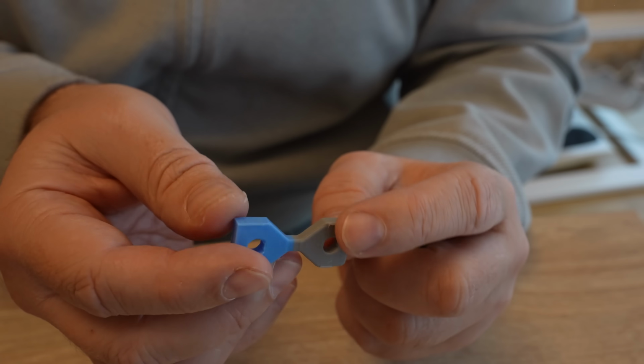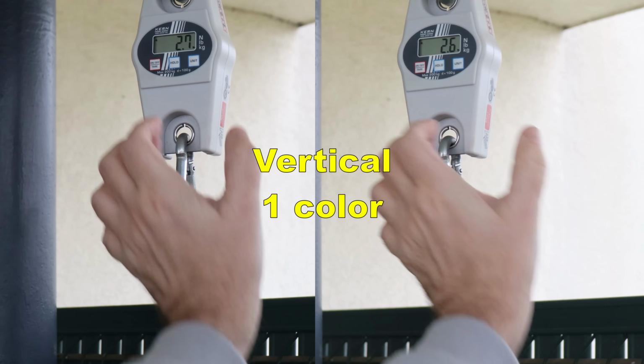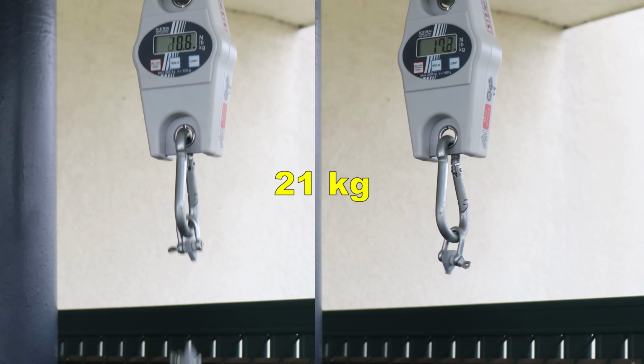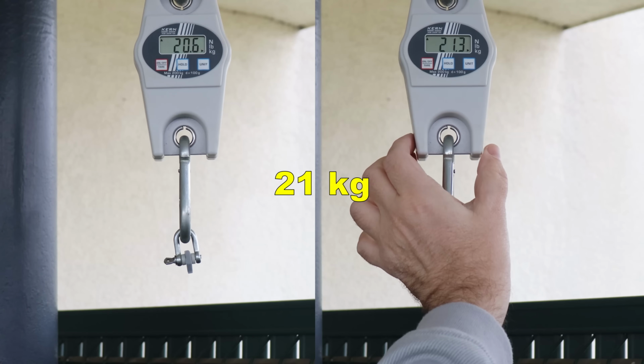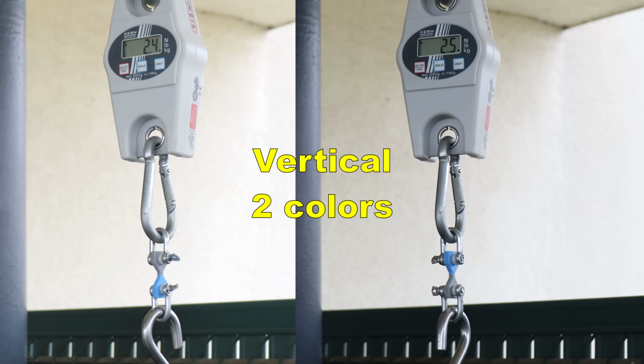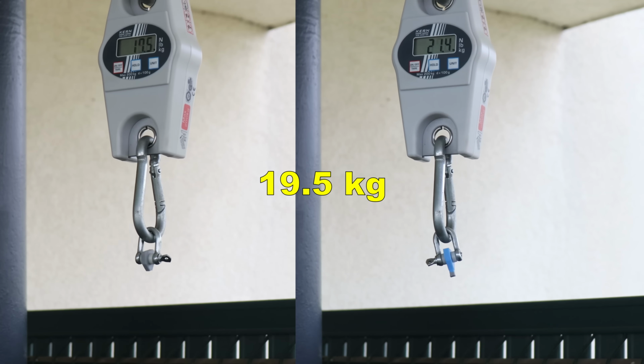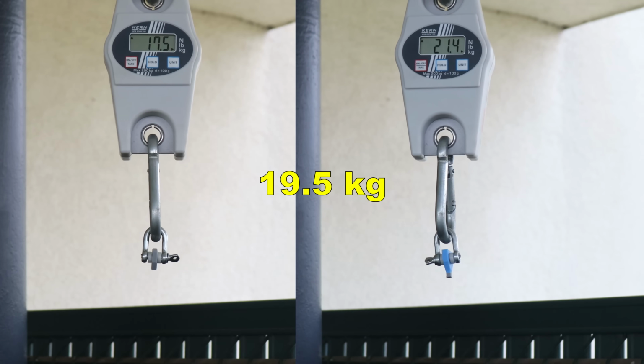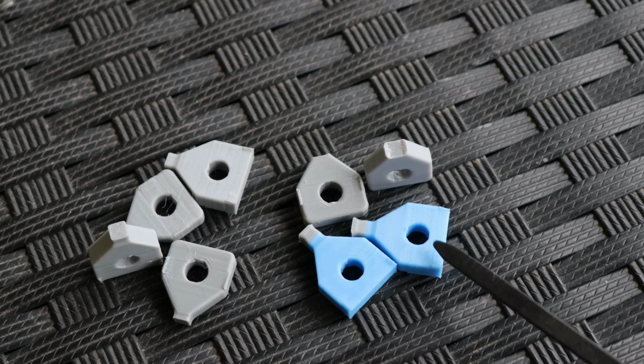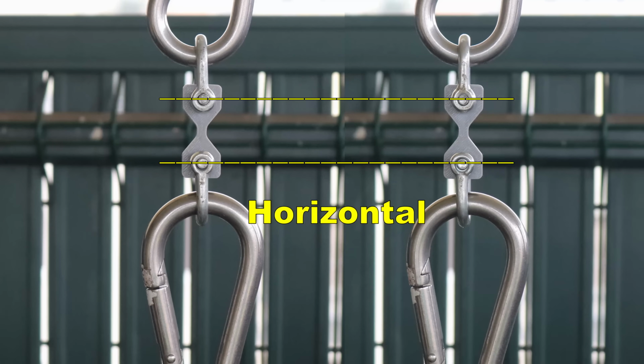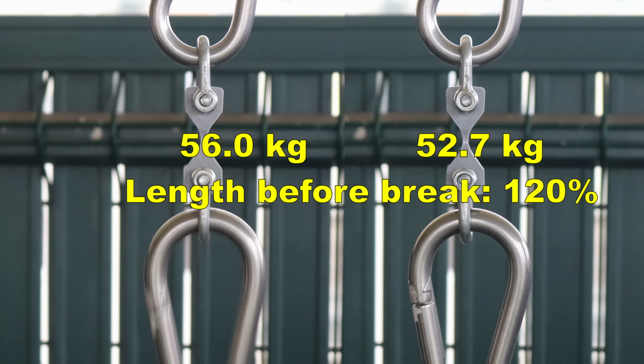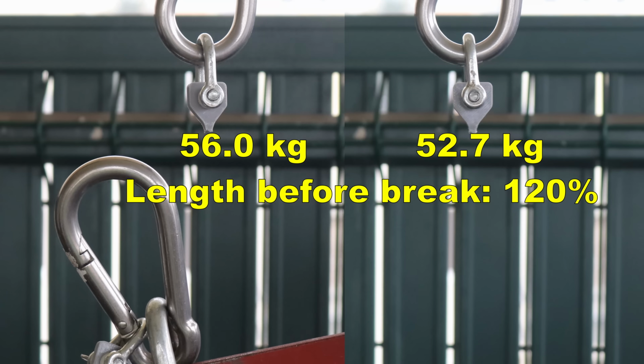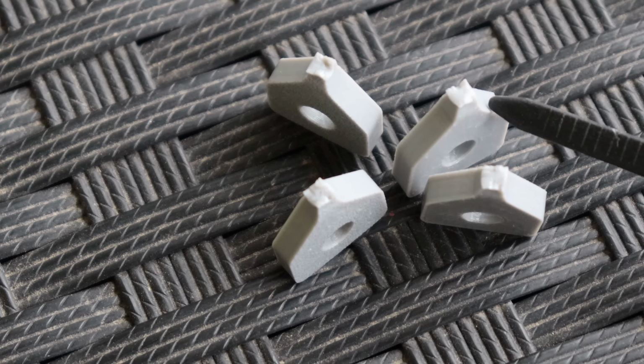And I'm starting with layer adhesion. I'm curious how this performs with two colors. This is still in single color, slightly above 20 kilograms. And this is the two color version. Very similar layer adhesion. But interesting, it did not break between two colors, but higher. And this one was printed in horizontal position. And I want to measure some prolongation before the break too.